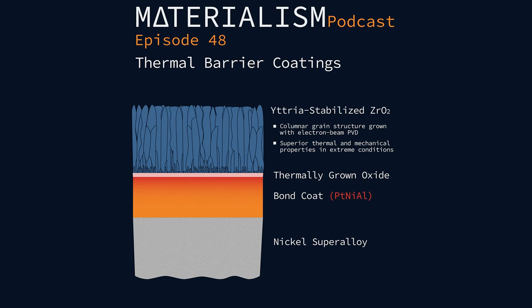So earlier you mentioned that they're not taking advantage of the transformation toughening properties of yttrium stabilized zirconia. Can you talk a little bit about that? Why aren't they? Yeah, I mean, most of the times when you use YSZ, you have this huge benefit of the fact that when a crack shows up in the material, we know that the mechanism by which it toughens it is that there's a transformation. The tetragonal phase is not supposed to be in the tetragonal phase at room temperature. It's only there because it's metastable.